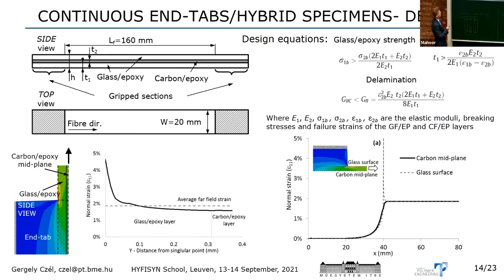And if you plot along a path, so it's across the thickness, the longitudinal strains, you can see that yes, at the surface of the specimen we have very high strains, but glass can actually go up to 4% strain, especially if it's very local, no problem, can go up to 4.5%, a good S glass. And then it drops down to even below the average far field strain in the carbon. So it's actually less likely that we have the failure near the tabs because of this tricky stress concentration and distribution near the tabs. So we are saved from this problem.